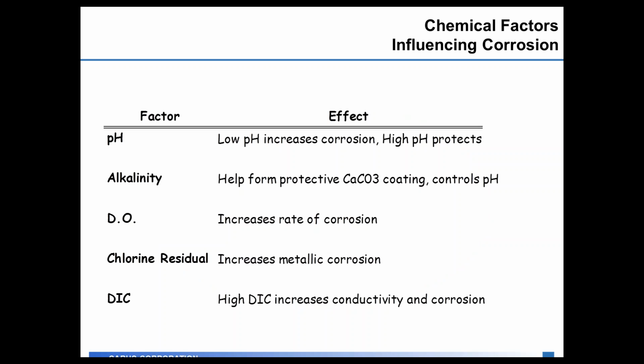Specifically, when we talk about chemical factors that influence corrosion, these are the main ones you typically look at. pH being the most common one. As we know, low pHs are acidic, and those would increase the corrosion rate on metals out in the distribution system. Typically, we think of higher pHs on the basic side of things as protecting the pipe by helping you to lay down a coating.